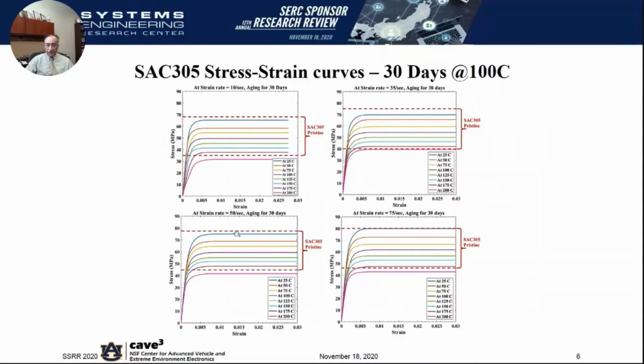Now, if I scan the graphs from the left to the right, both in the top row and the bottom row, one can see that as the strain rate changes from 10 to 35, from 35 to 50, 50 to 75, my ultimate tensile strength is going up, which basically means my threshold to failure is increasing with the increase in strain rate. Also, my effective modulus is changing, which means the structural stiffness of the alloy is changing as well.